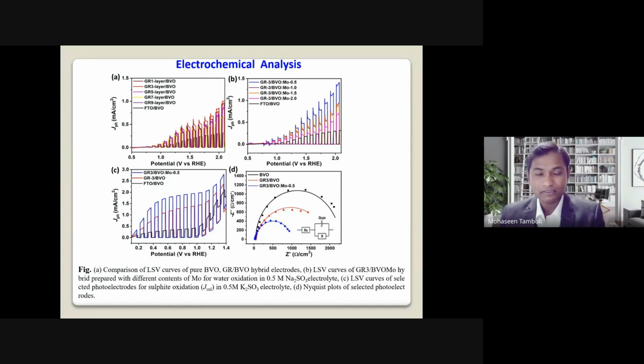You can see the small semicircle here. The small semicircle in blue color is the optimized graphene BiVO4 and molybdenum photoelectrode. A small semicircle means higher conductivity, meaning high charge transfer. If you see the red color here, it shows the graphene BiVO4, where the conductivity is a little less compared to the optimized graphene BiVO4 molybdenum electrode. But for pure bismuth vanadate, it shows low electrical conductivity. So with the addition of graphene and molybdenum, the conductivity increases.